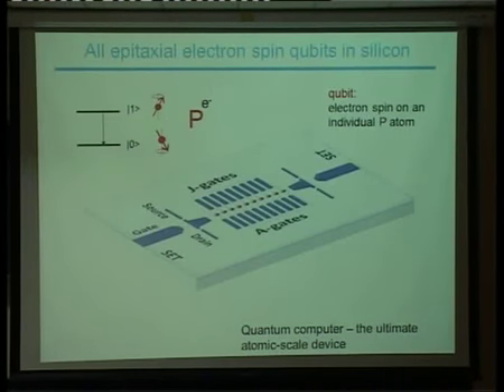The key difference with the other phosphorus donor systems is that here we're actually placing all the donors down on a single crystal silicon surface. And we're aligning to those individual phosphorus donors, we're aligning these A and J gates in the plane. So they're all patterned by STM in one step. And at the ends, we have our single electron transistors to be able to do the readout.